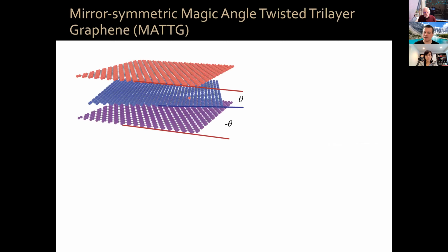So this is the structure, okay? Now it is 3 layers of graphene where the bottom and the top layers are exactly aligned, 0 degrees with respect to each other, and all of the carbon atoms in layer 3 are on top of all of the carbon atoms in layer 1, okay? The middle layer is rotated by an angle, theta, okay? So from the top to the bottom, you add the second layer rotated at an angle minus theta, and then you add the third layer rotated back by theta so that it's exactly aligned with the bottom layer. This structure has mirror symmetry with respect to the middle layer, okay?